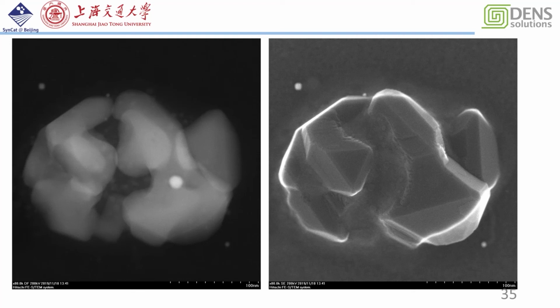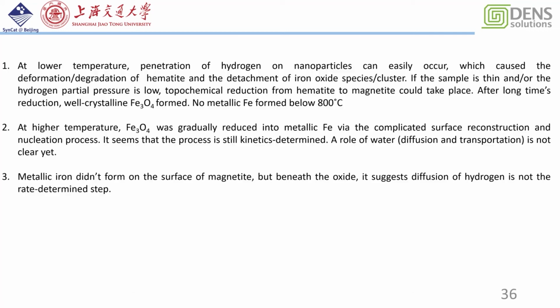To do that, they found a very interesting thing. This is a big iron particle formed inside the bulk of the magnetite, not on the surface. It suggests that the diffusion is not the rate determining step for the reduction, but another process. So we guess the water maybe plays a very important role to stop the complete reduction of the iron oxide to iron. But presently we don't have other evidence to prove that.